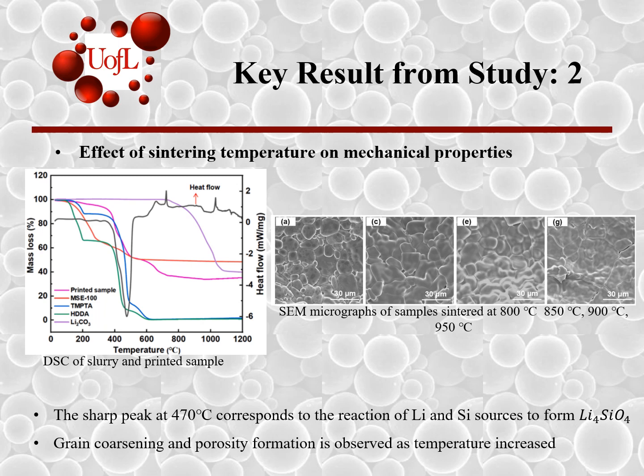We see a sharp peak at about 470 degrees Celsius. This corresponds to the reaction of lithium and silicon sources to form the target material. Beyond this point, the incremental heat rate is maintained slow and the dwell time is maintained higher to ensure the complete synthesis of the target material. The samples are sintered at different temperatures, after which the SEM micrographs are taken as shown on the right. As seen, the grain size keeps increasing with an increase in temperature, and beyond 850 degrees Celsius we see presence of porosities in the structure.